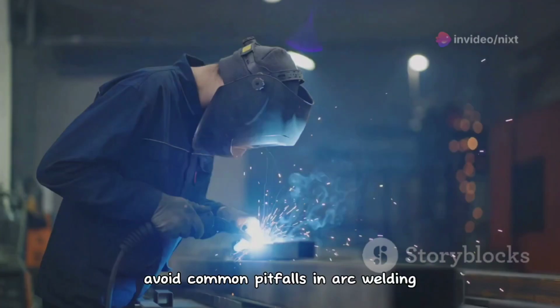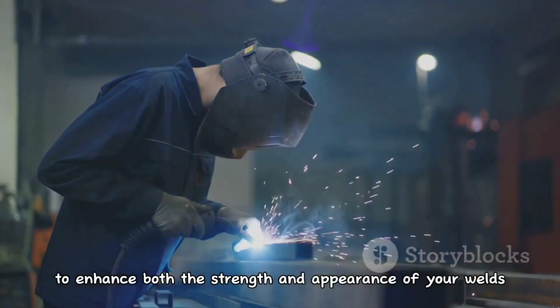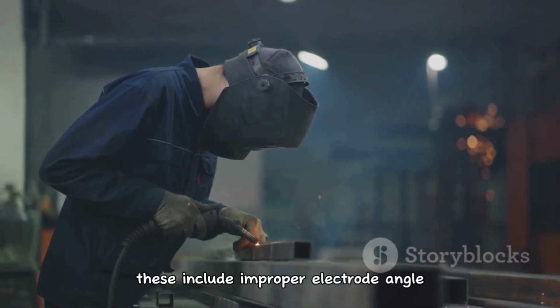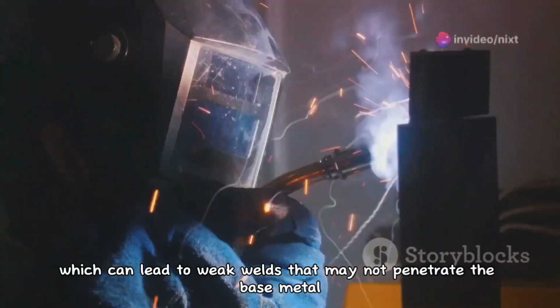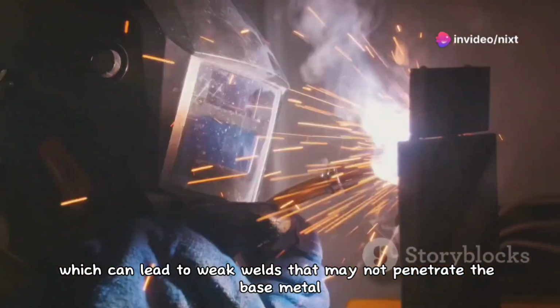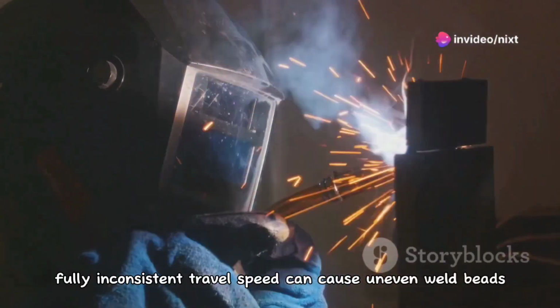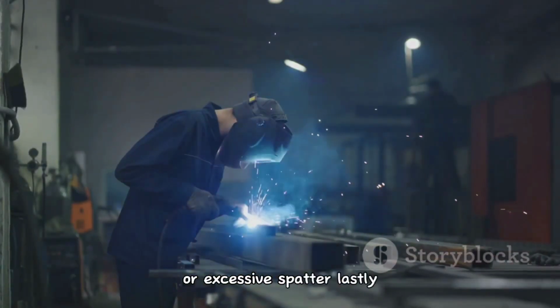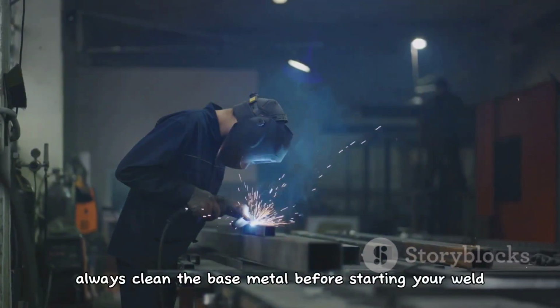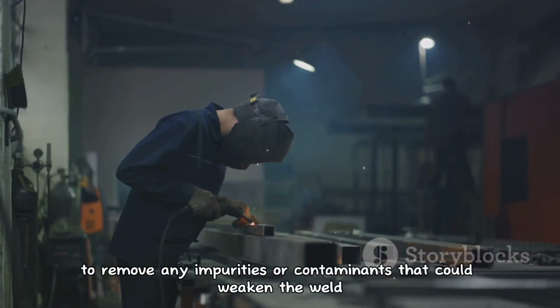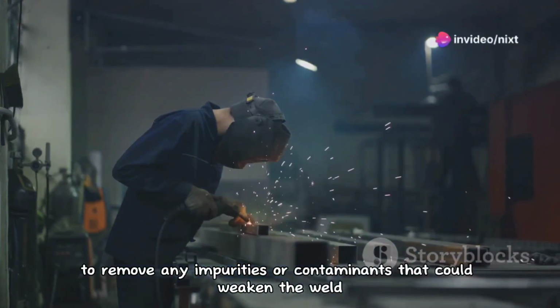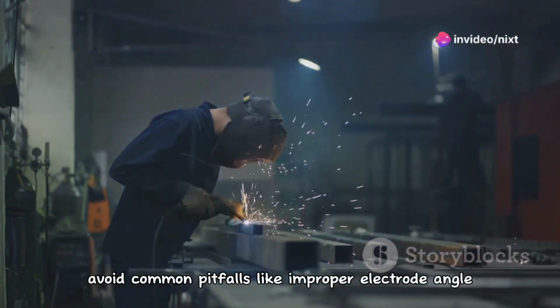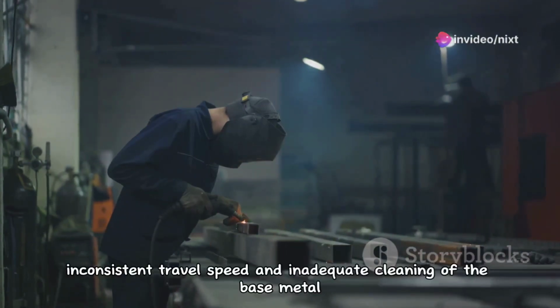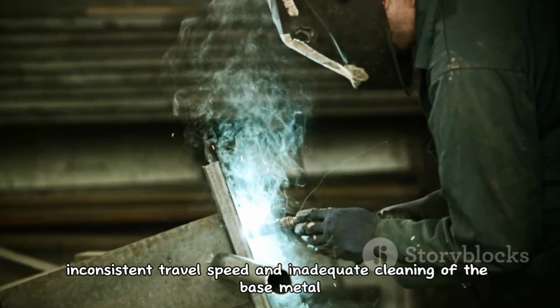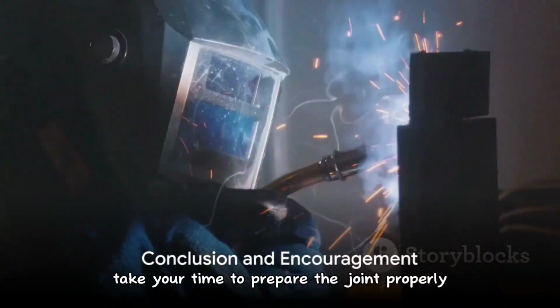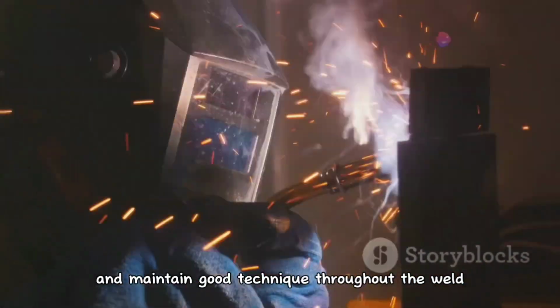Avoid common pitfalls in arc welding to enhance both the strength and appearance of your welds. These include improper electrode angle, which can lead to weak welds that may not penetrate the base metal fully. Inconsistent travel speed can cause uneven weld beads or excessive spatter. Lastly, always clean the base metal before starting your weld to remove any impurities or contaminants that could weaken the weld. Take your time to prepare the joint properly and maintain good technique throughout the weld.